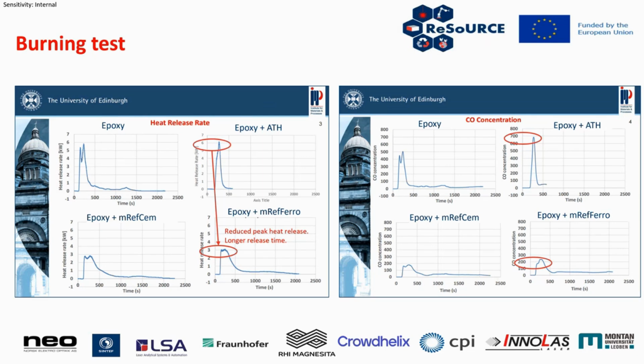But what you can then see is if you actually look at other data points in there, so for the heat released, you can see because of the thermal insulating properties here, we don't get as high of a spike of heat release, but we get that over a prolonged period of time. So we're elongating the burn effectively. And you can see that the same is seen in the carbon monoxide concentrations, where the actual peak of the data is lower, but we've broadened out that release. So we're not suggesting that we fully replace aluminium trihydrate with these materials, but these materials could be of interest to mix with aluminium trihydrate to improve already good thermal properties of materials by extending that release.